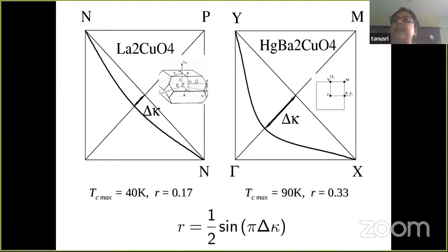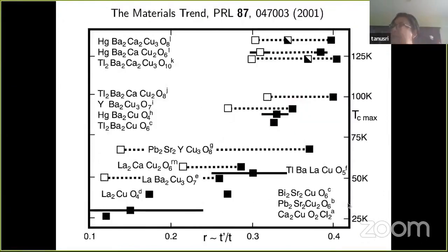And this delta K can actually be defined with the parameter R, which is quite different between the lanthanum compound and the mercury compound. And we did basically the same exercise for all the known hole-doped cuprates long back in 2001. If you just follow the black symbols, for the sake of time I'm not going to explain this curve in detail. Here in the y-axis, this is a semi-empirical curve, in the sense that the y-axis is the optimal Tc at optimal doping, which is measured,